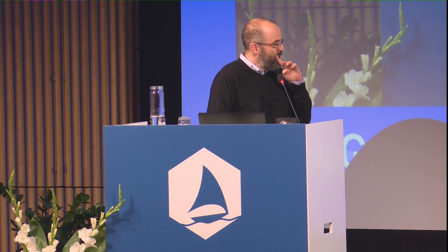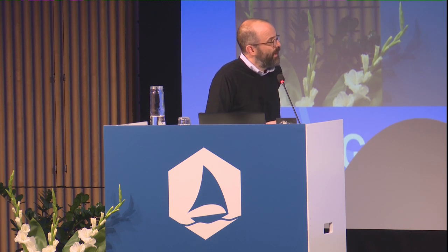So this is an interesting thing to think about, going back now to around 2010. There were a handful of papers that pointed out that actually if you can make such a system, the crystal structure of the composite heterostructure is pretty interesting in a number of ways. This is work by Jean Millet in which he pointed out that you actually get some kind of quasi-crystal ordering if you go to the right angle, 30 degrees mismatch. This looks like a non-periodic kind of Penrose tiling.